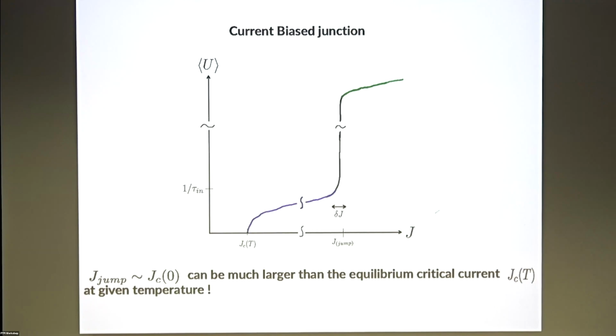And I would like to turn your attention to a characteristic feature of it. Again, I am not 100% sure about the statements which I would like to make, but my impression is that most of the experimenters, maybe all of them, measure critical current wrongly. Not only in Josephson junctions, but in films in general. And the reason is this, so look here. This is the region which I'm speaking about. These voltages are very small. How small, I don't know, and I will comment on this later. But anyway, the difference between the critical current and the current where it jumps would be parametrically big. But you have to measure the IV characteristics at small voltages. How small? If you take this tau inelastic literally, it is a really small voltage.